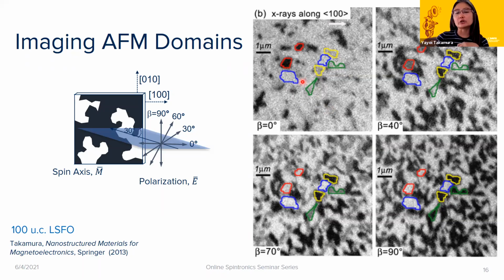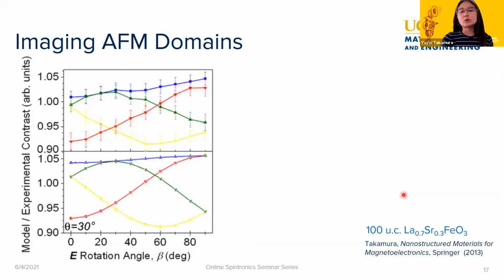But if I look at the domain which is directly above it, the red one, right? So that one is very different. It starts very dark, right? And it gradually gets lighter, right? And so here at 90 degrees, they're actually almost the same contrast, right? And so again, we know that we have this cosine squared dependence, right? So what we can do then is map, as a function of that beta angle, the polarization angle,